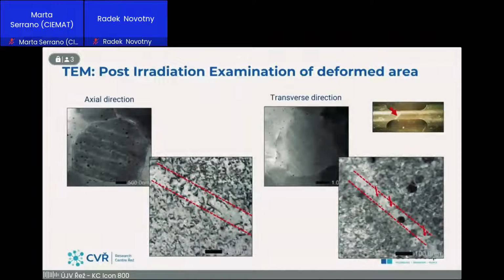So here we can study in detail the way that loops might get annihilated or dragged by dislocations, and they produce a clear zone free of these defects. So these free channels serve as a path for dislocation glide. So this is the strain localization at the grain scale.